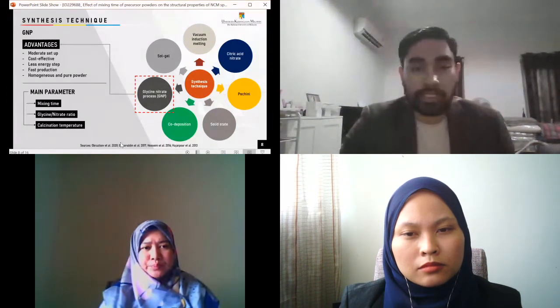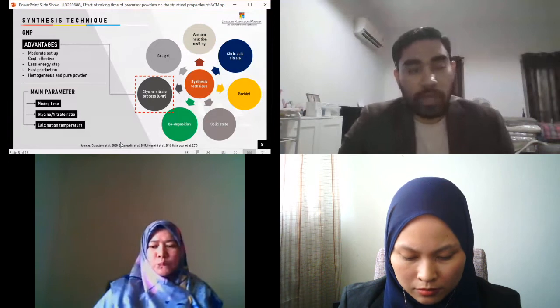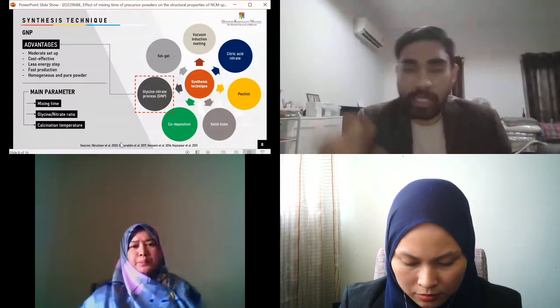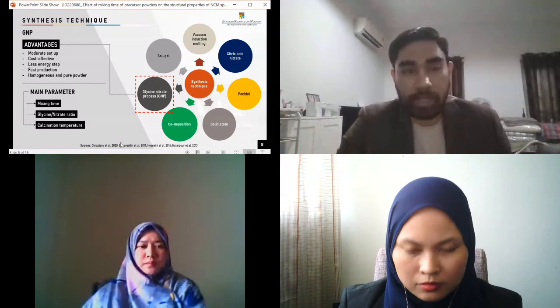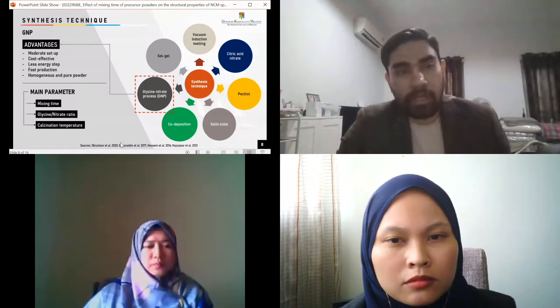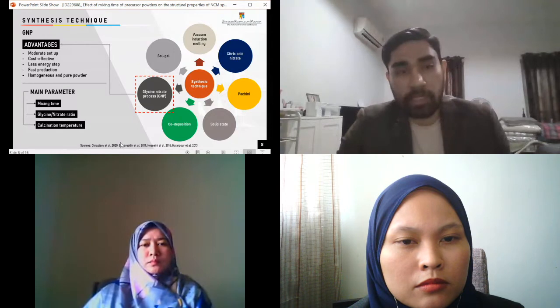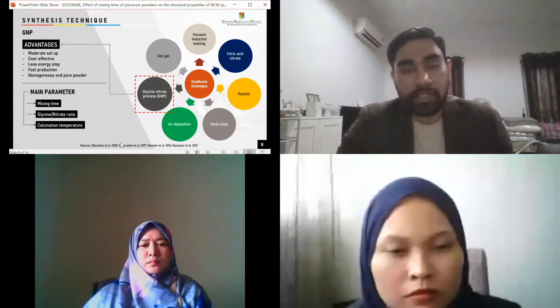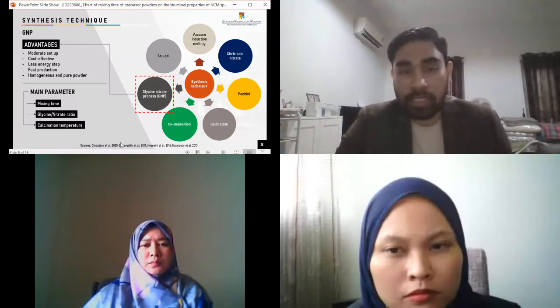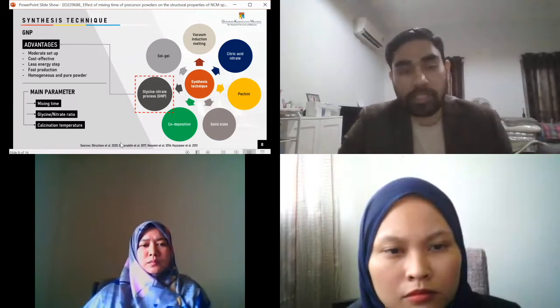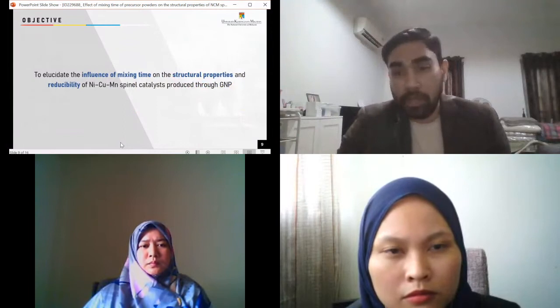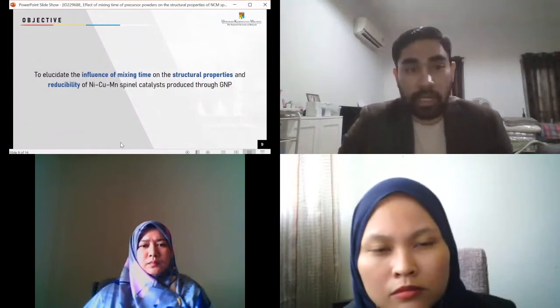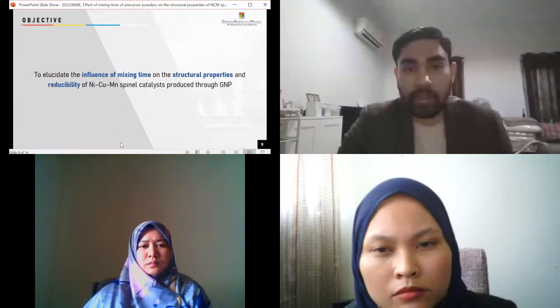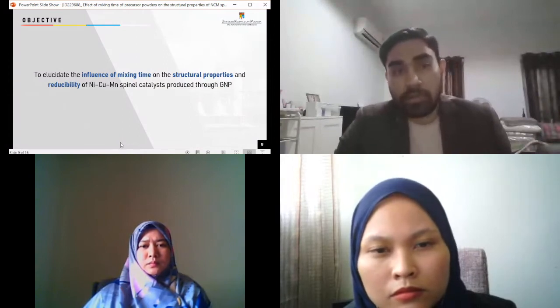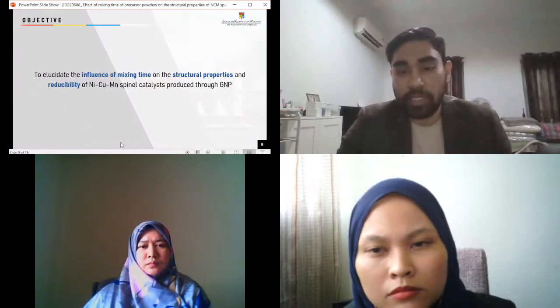However, when we study this technique, we have to consider the three main parameters which can influence the structure of the spinel. The first one is the mixing time, followed by the glycine nitrate ratio and also the calcination temperature. For this presentation, I will focus more on the mixing time, which is the first part of our project. Therefore, I hope to elucidate the influence of mixing time, not only on the structural properties, but also the reducibility of the nickel copper manganese spinel catalyst produced through the GNP process.